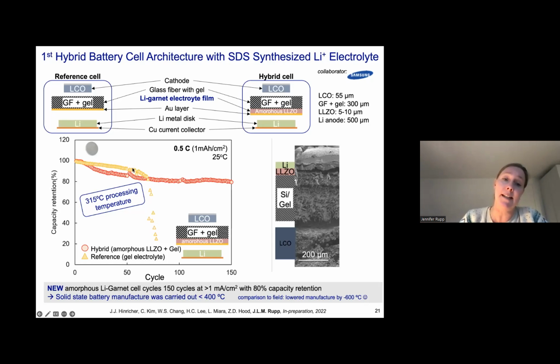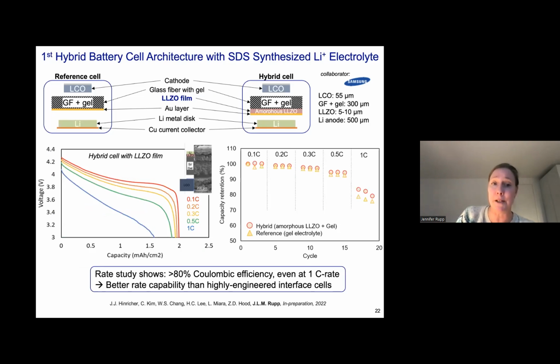And this is what we can see. In the reference cell, in yellow, sorry, you see that the cell is losing performance. The Samsung cell was tested in Burlington at around 80 cycles. However, the other cell is going and is measurable for a high number of cycles. It's just the very first test, so it's a non-optimized cell, but it demonstrates that you can make the films in this way and bring them into cells.